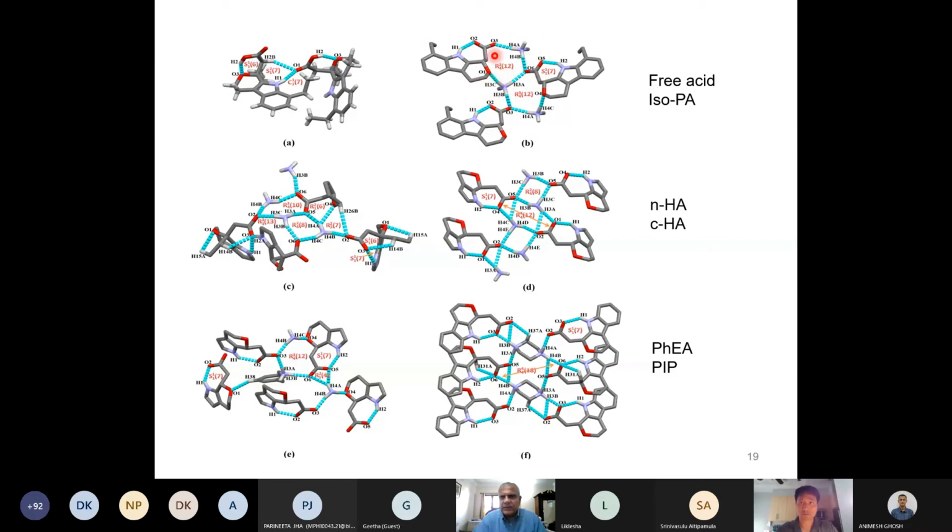So essentially, the drug molecules surround the ammonium ion in the isopropylamine, and similarly the hexylamine, N-hexylamine, cyclohexylamine, phenethylamine, and piperazine. So all these are in one way or another NH groups which are hydrogen bonded to the drug. Each structure is slightly different, but the essential point is that it has strong ionic protonated nitrogen NHO, or O minus, hydrogen bonds.